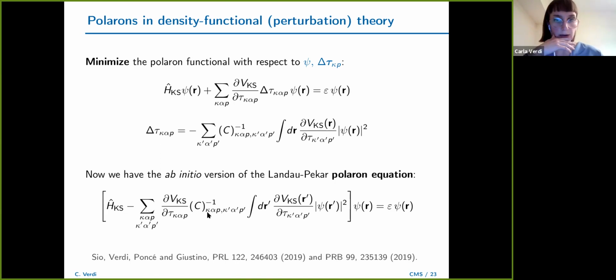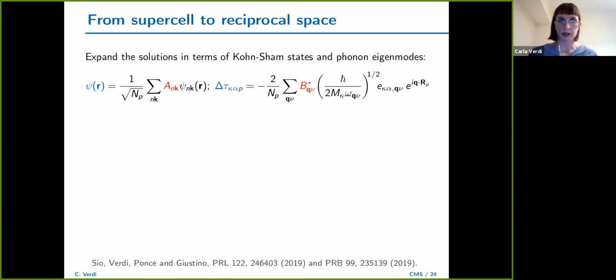Now we could solve this, but it's not what we want to do because, again, it's done in a supercell. Now the problem is that when you add an electron in a supercell, the self-localization can also depend a lot on the size of the supercell that you're considering. To say it even more easily, imagine that you have a large polaron that is localized over quite a few lattice parameters. Well, then you would need a very large supercell to describe this object, and this is simply unfeasible from ab initio. But there is something clever that you can do.